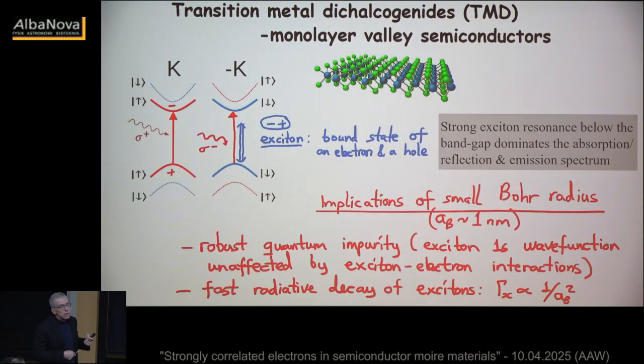All right, so what is special about these materials? In the monolayer limit, they're direct band gap semiconductors, and for molybdenum ditelluride, even in bilayer, they're direct band gap semiconductors. This will become very interesting. And what is important is that the band minima are at these high symmetry points of the Brillouin zone, the K and minus K points, which are the time reversal symmetric counterparts of each other. So you can think of it this way: if you consider an electron in K valley, this is an electron that rotates, say, in the counterclockwise direction between different sites. In minus K valley, it rotates in the clockwise direction.